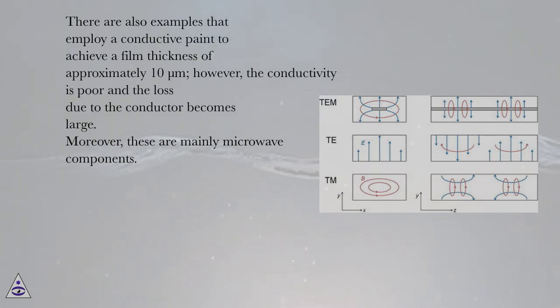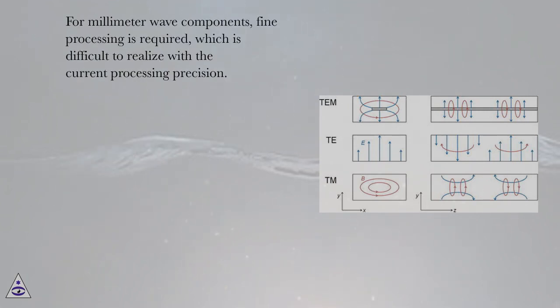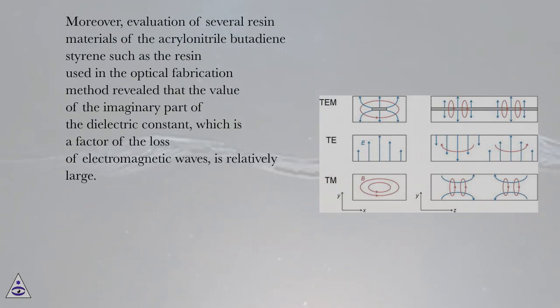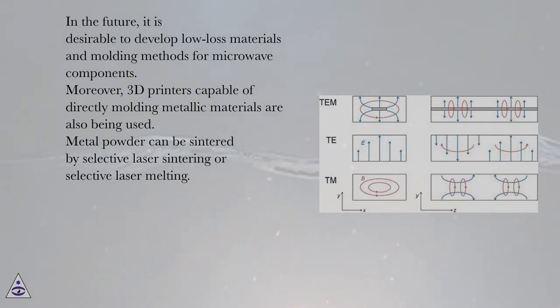There are also examples that employ a conductive paint to achieve a film thickness of approximately 10 μm, however, the conductivity is poor and the loss due to the conductor becomes large. Moreover, these are mainly microwave components. For millimeter wave components, fine processing is required, which is difficult to realize with the current processing precision. Moreover, evaluation of several resin materials such as acrylonitrile butadiene styrene, and the resin used in the optical fabrication method, revealed that the value of the imaginary part of the dielectric constant, which is a factor of the loss of electromagnetic waves, is relatively large. In the future, it is desirable to develop low-loss materials and molding methods for microwave components.